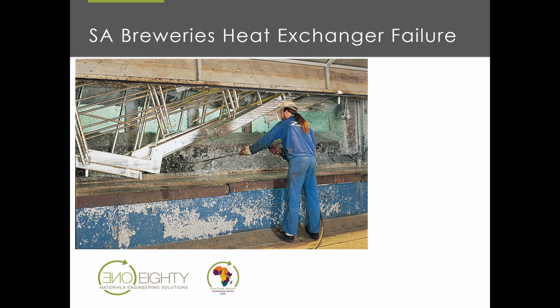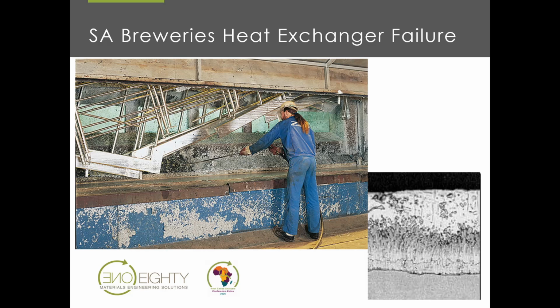The problem is managing the acid baths is expensive. The acid has to be disposed of in an ethical way, and it's an expensive thing to do. So the galvanizers tend to run the acid bath to almost end of life and beyond end of life, where there's no more acid left to effectively clean the heat exchangers. Once the item has gone into the acid bath, it is then rinsed a few times, and then it goes into the molten zinc bath.